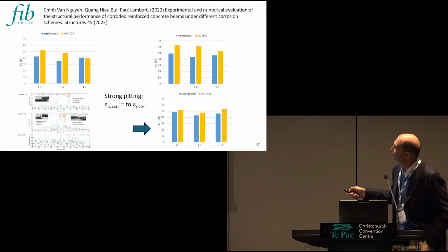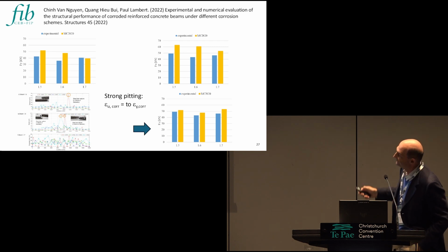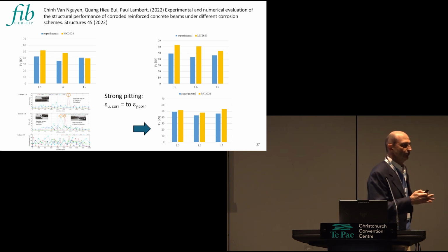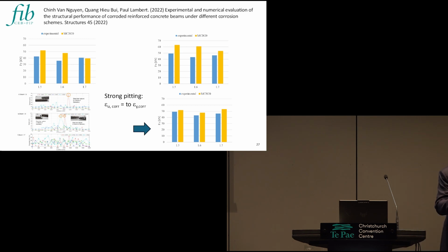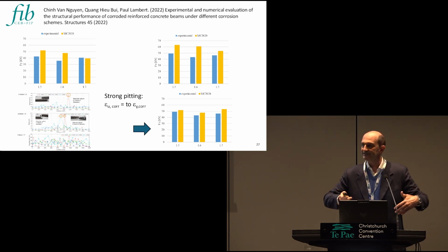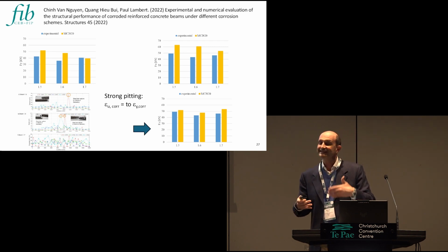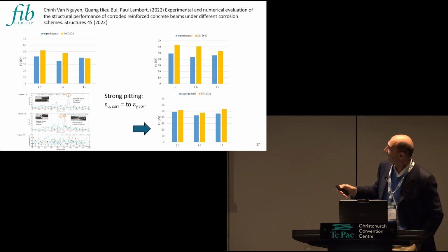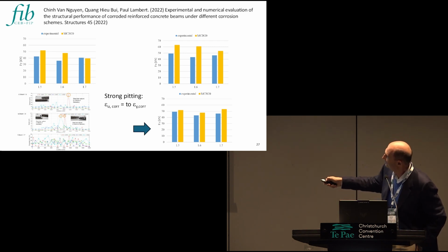That is the situation of some tests performed in 2022, because the problem is sometimes that you check the results, and you can't take all the results in a database without having a critical analysis of the results. In that case, they performed a very strange accelerated corrosion that gives a more uniform corrosion instead of some localized peak, only one peak.